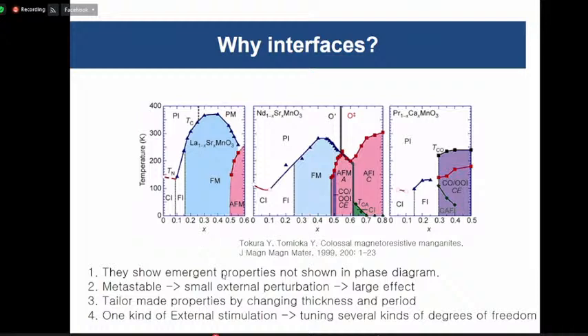First, interfaces show emergent properties not shown in the phase diagram. In these phase diagrams we cannot find any ferroelectricity, but we can generate ferroelectricity, ferromagnetism, and also spin glasses. Also, the interface is metastable. It's not like a bulk. So if we give a small external perturbation, it gives rise to large effects. Also, we can tailor properties we need just by changing the thickness or period.